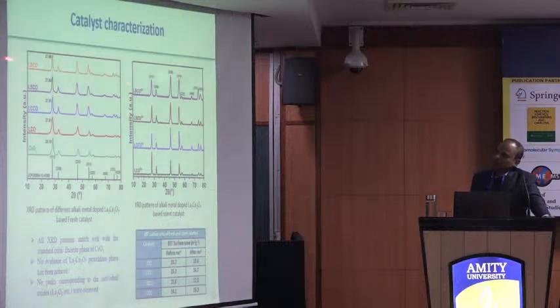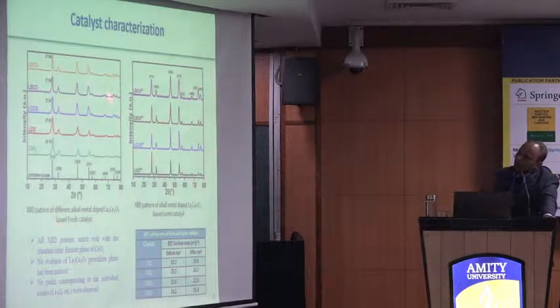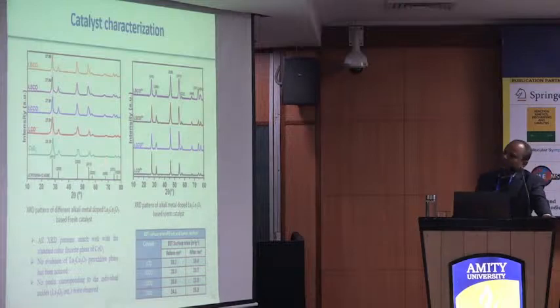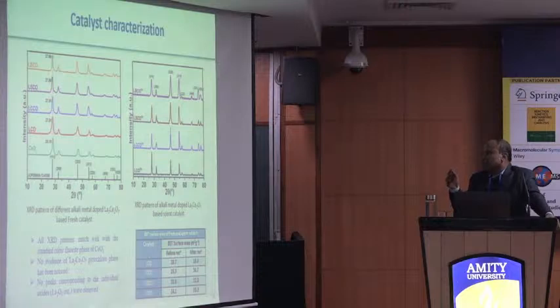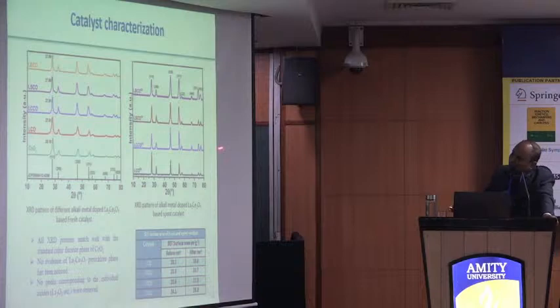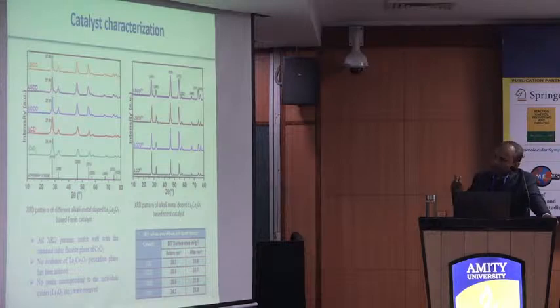This is the XRD for all the catalysts, and this is the spent catalyst. We can see that all the XRD belongs to CeO2 and fluorite. That means the lanthana and ceria are present in very small amounts or dispersed on the catalyst, and also from the spent catalyst, that means the catalyst is stable. We have done this reaction for 200 hours and I found that the catalyst is very stable.